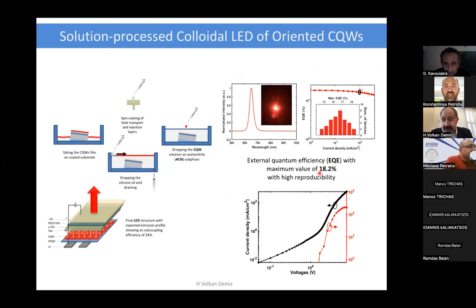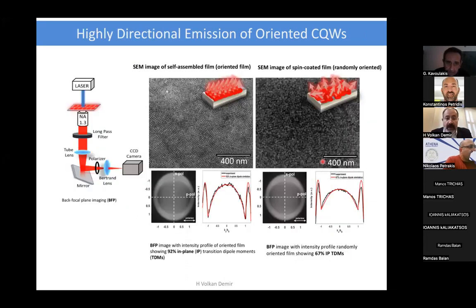The best reported previous result is indeed below 10%, in the range of 7 to 9%, when you don't have this orientation. So this technique, we believe, could be quite exciting to make future devices too.